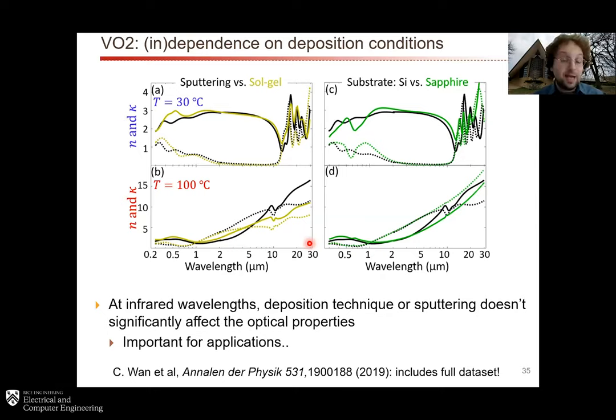So this is actually quite exciting because it means that all of a sudden you can use this literature data set, whether it's ours or from other people's measurements in the mid-infrared between about 2 and 11 microns, and you can apply it to your own design, and you can be reasonably confident that the data set is representative of the material that you have in your own lab. So we thought that was exciting.